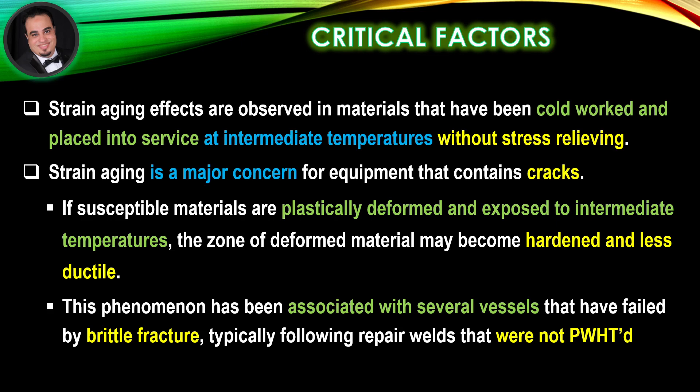the zone of deformed material may become hardened and less ductile. This phenomenon has been associated with several vessels that have failed by brittle fracture, typically following repair welds that were not post-weld heat treated.